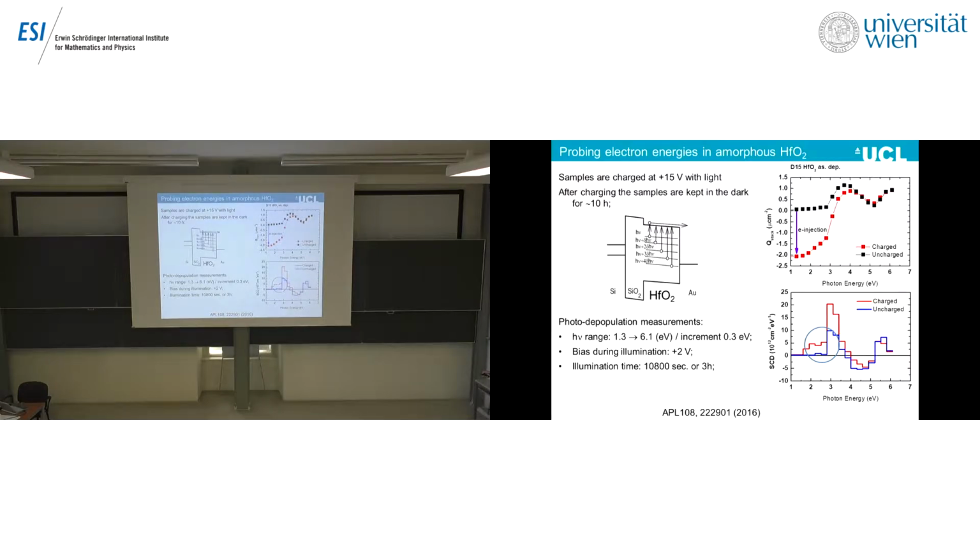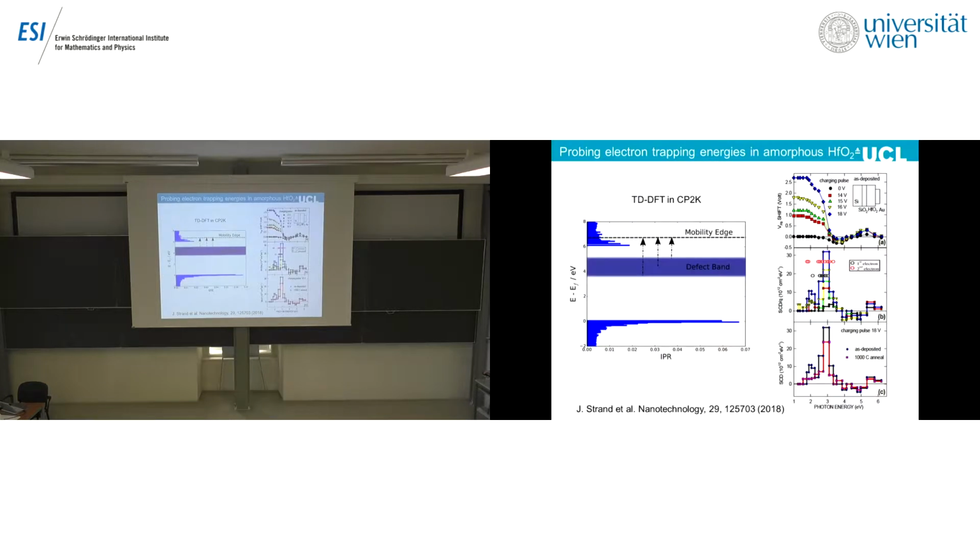So this is the spectrum of sites which are produced in the band gap as a result of negative charging of the system. You see that there are sites at around 2 volts up to 3.5 volts in depth. So these are these maxima. Here they correspond to these electron traps. So this brings quite a fundamental question about how to deal with these disordered systems. And so what is actually measured? Here is a band of trapped electrons, both single electrons and bipolarons, which we have seen here.